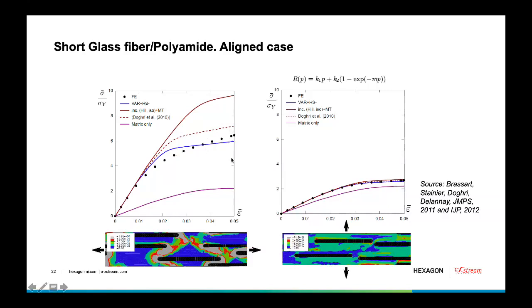If you look at the tension test in the other direction, the direction transverse to the fibers, then again this is the response of the unreinforced matrix. The dots are the finite element results. This is our reference when we try to verify mean field models. And the predictions of the mean field models, in this case, are all close to each other and close to the finite element results. Actually, this case of short fibers, which means an aspect ratio, length over diameter of fibers, of the order of 20, let's say,